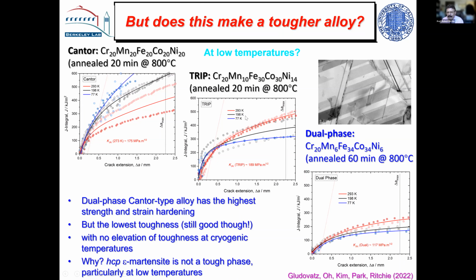These two have the added mechanism of the transformation to form a hexagonal phase, but it's not as good as the original alloy, which didn't have so much of that. And the reason is that the TRIP effect is beneficial. It absorbs energy, it gives strain hardening, but the resulting phase is epsilon martensite, which is a brittle phase. So if you're going to have this mechanism, you don't want too much of it, because that gives you an embrittled material.